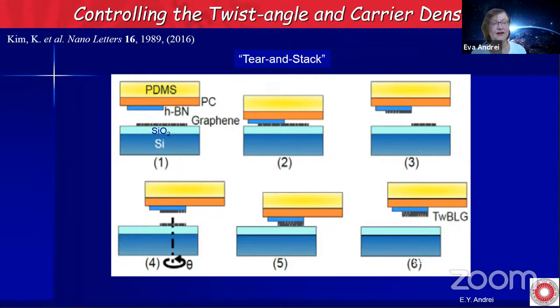So you put down a graphene layer, you take boron nitride, which is a sister material, and you heat it up. These are some polymers. You press it down, now the graphene layer sticks to the boron nitride, lift it up, you've torn it in two pieces, and now you take the bottom piece, it's sitting on a goniometer, you rotate it by whatever twist angle you want, and we have huge control over that, and then you stick them back together, and that's how you create a twisted graphene layer with a pre-designed twist angle.